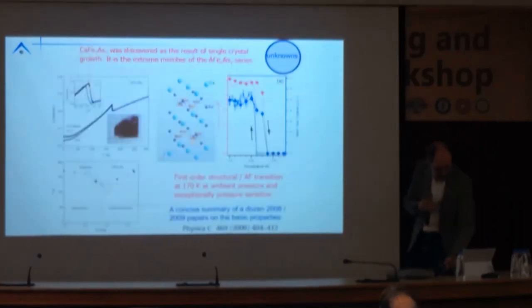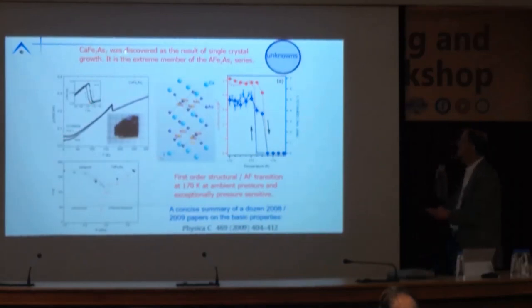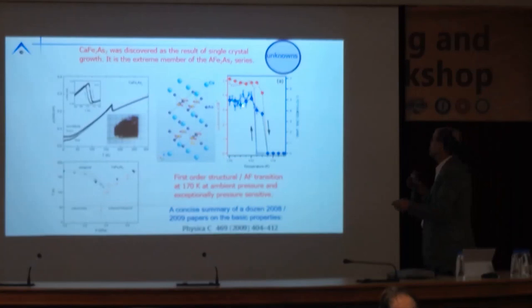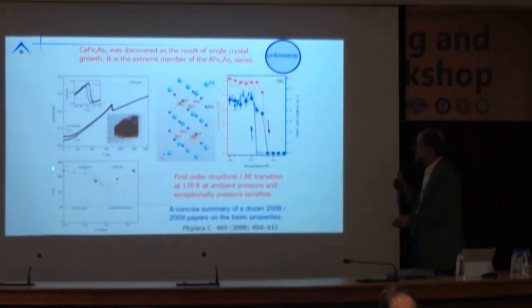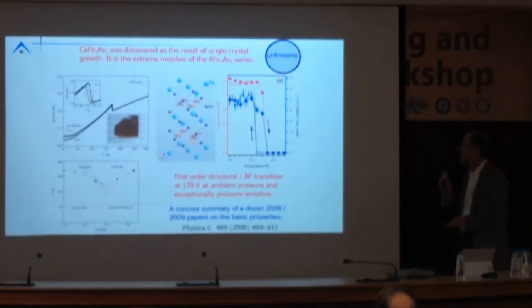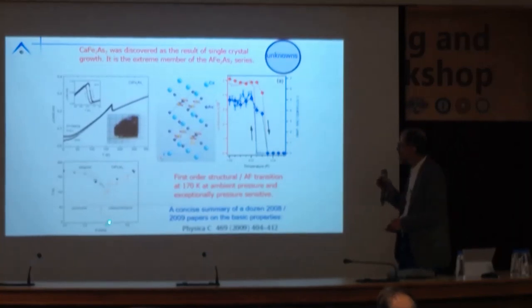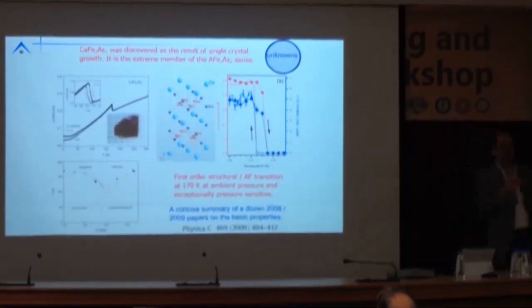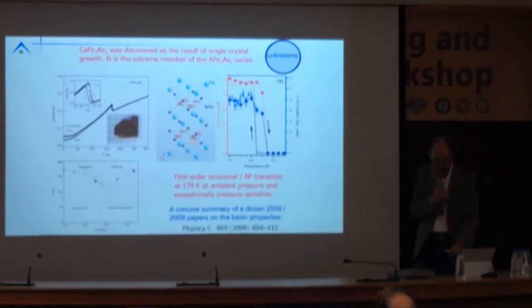Can they be made? It turns out calcium does make. We were able to discover the structure growing in single crystal form, and it's an extreme example of an alkaline earth iron arsenide 122 material. You have a strongly coupled first-order magnetic and structural phase transition. In addition, this material is one of the most pressure sensitive, having one of the smallest c lattice parameters, and with very little pressure, about 0.35 GPa, you can go from a tetragonal to a collapsed tetragonal phase, which completely changes the magnetism and superconductivity.